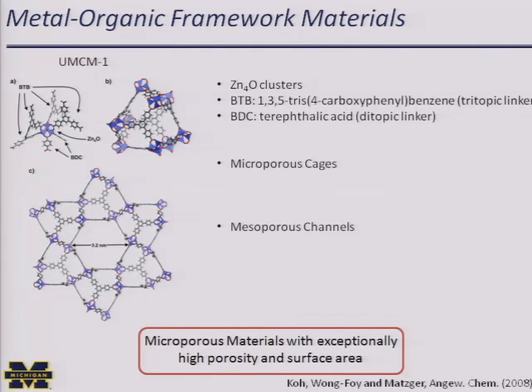And the exciting thing with these materials is twofold. From a practical standpoint, these are microporous materials with exceptionally high porosity and surface area. So the surface area here is over 5,000 square meters per gram. So this is a large, large area that doesn't even mean anything to me yet. But the point is that it is very useful for catalysis, for separations, for gas storage and hydrogen fuel cells. So we can think about lots of things to do with these metal organic framework materials.